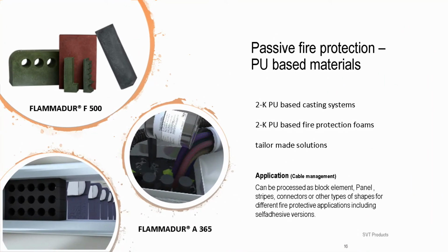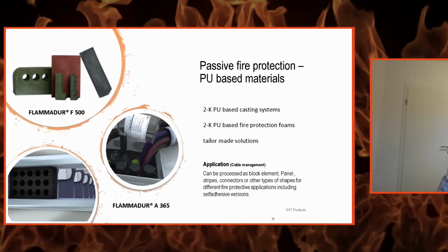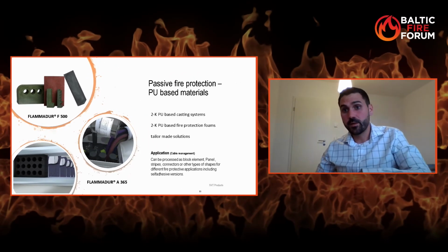Here are some other products that we can use. For example, that's a PU-based foam, or a PU-based casting system. The casting system you can use, for example, for cable management, and the foam. We have some projects right now where we cut this foam by water jet. We have a water jet cutting machine in one of our production sites, and we can cut these kinds of materials perfectly in the form of the cells. So you can cover the cells with this foam, and if you get a thermal runaway, the foam, which is also an intumescent material, is between the cells and stops the propagation from one cell to another cell.